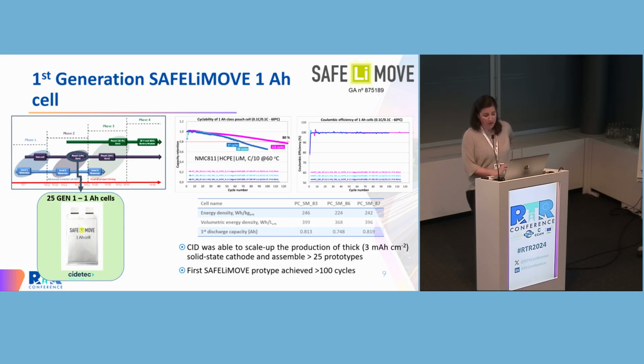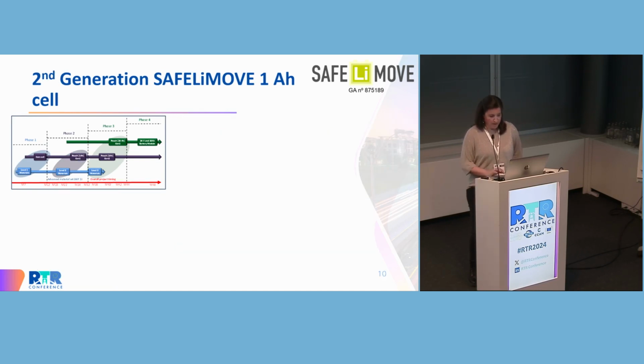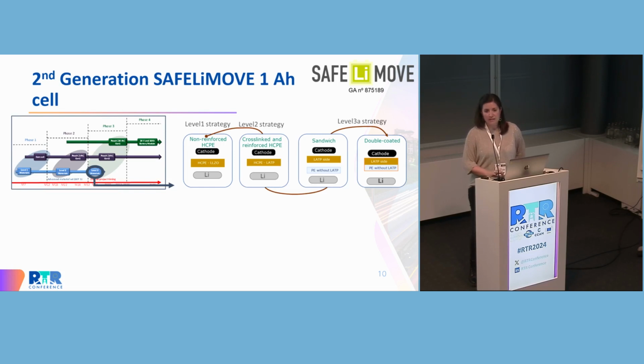We were around 240 watt-hour per kg, while in the case of the volumetric energy density, we were close to 400 watt-hour per liter. And the key point is that from the level 1 materials to this second generation of materials, we were able not only to scale up, but also we need to consider that we tripled the loading of the cathode, we decreased the thickness of the lithium metal, and we were able to reach more than 100 cycles with these energy densities.